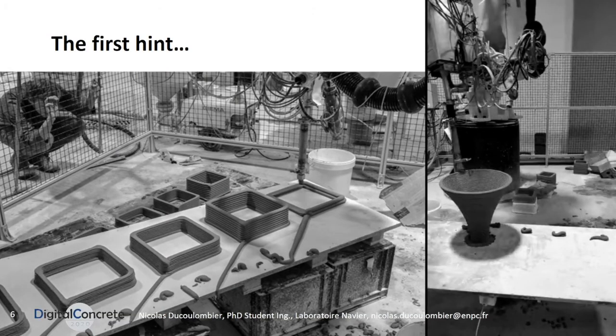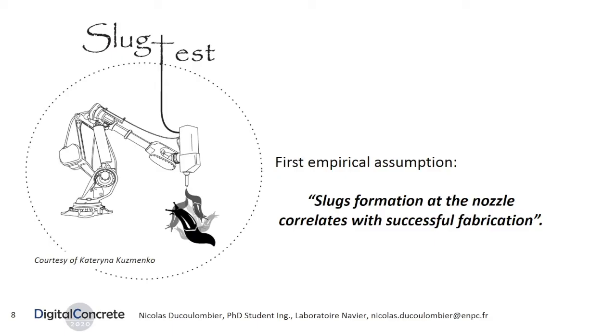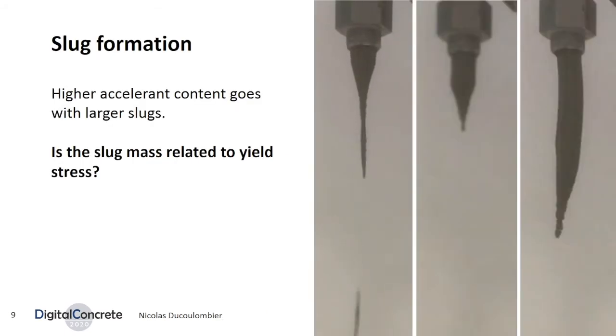The initial idea came from the fact that each time we had a successful printing, we noticed the presence of small slugs around the printing area. They were generated before the printing, during the approach, when the nozzle was still far above the ground. This is the idea of the slug test, and the first empirical assumption: slug formation at the nozzle correlates with successful fabrication. We therefore decided to study in depth the formation of these slugs and its underlying physics.